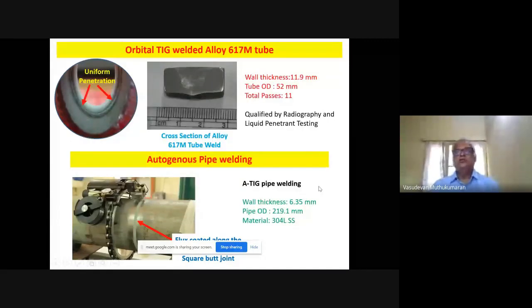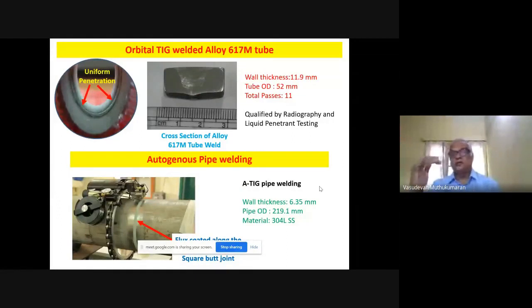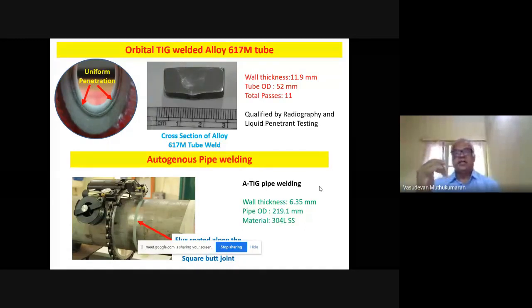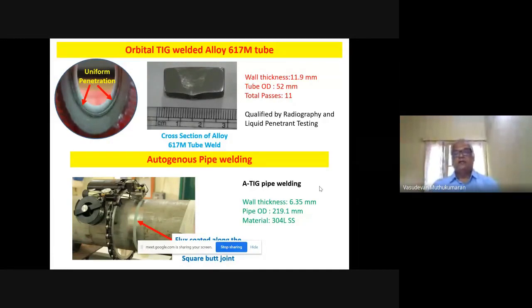Only thing, you have to optimize the process parameters, because after you cross the second and go to the third quadrant, the heat build-up aids the penetration in the third and fourth quadrant. So you have to reduce the current levels when you go to the third and fourth quadrant to get full penetration and to avoid melt through, things like that. So again, we successfully used this process for welding of these components.